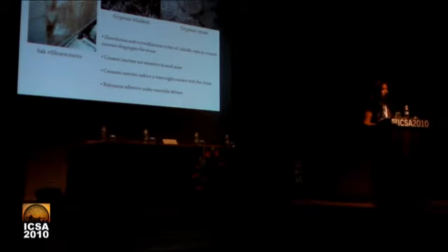These soluble salts are the cause not only of unaesthetic efflorescence, but also of disgregation of the stone itself. In fact, in humid environments, these salts dissolve and circulate within the pores of the stone. When the water evaporates, they crystallize and increase their volume, and this increase in volume causes the disgregation of the stone itself.